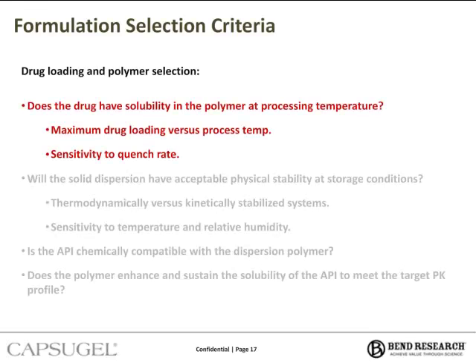So this slide shows some of the questions we begin to ask ourselves during formulation selection. Now the first question is, does the drug have solubility in the polymer at the processing temperature? And what we're really getting after here is, what is the maximum drug loading versus process temperature we can use, and how sensitive is that going to be to a quench rate?